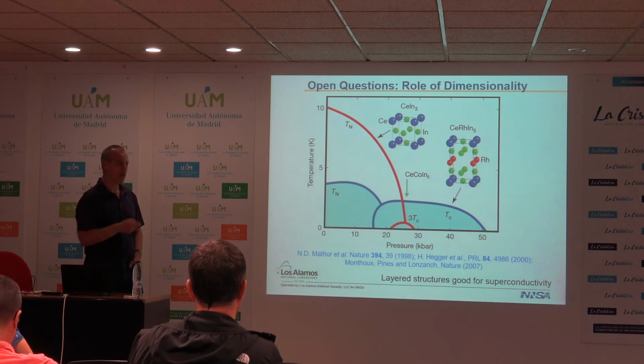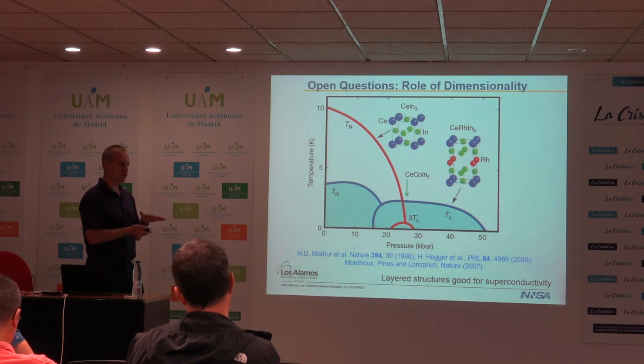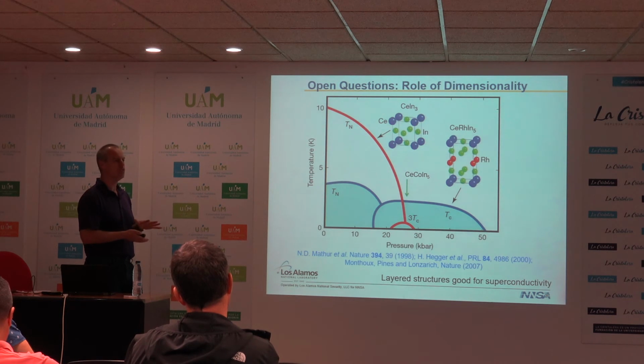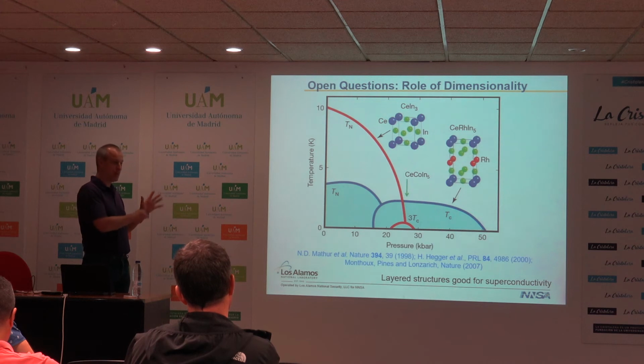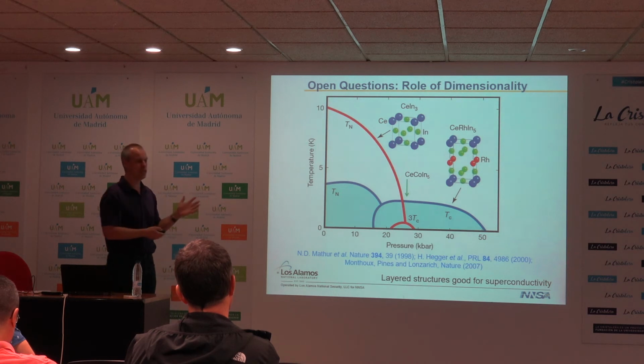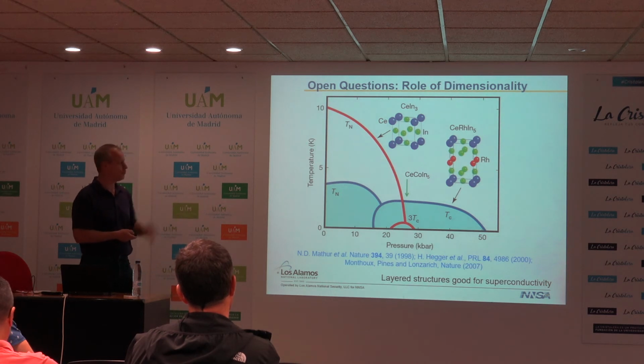So it was Yuji Matsuda, and unfortunately he's left, but he was able to make superlattices of, say, cerium rhodium indium 5 and cerium cobalt indium 5. And they see very interesting effects because now you break the inversion symmetry, and there were arguments that this leads to a Rashba coupling, and he sees interesting behavior in HC2 in these thin films. In general, unfortunately, MBE is very difficult for these compounds, and he's to date the only group that has been able to make really beautiful thin films of this.